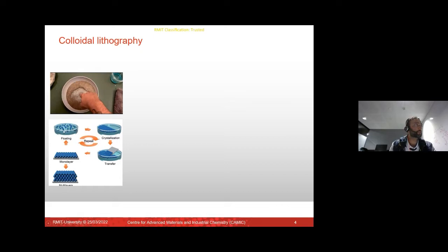So how do we do that? We use the air-water interface by depositing our colloids on top of the water surface. And in order to bring them into a compact form, we use a surfactant, depending on the surface charge of your colloids, and that brings it all together. As you can see on the figure above, this guy has actually put his finger in soap beforehand, so he's got surfactant on his finger, and he puts it into the water, and all the colloids or particles on the air-water interface get compacted together. In a similar fashion, we've done that over here.